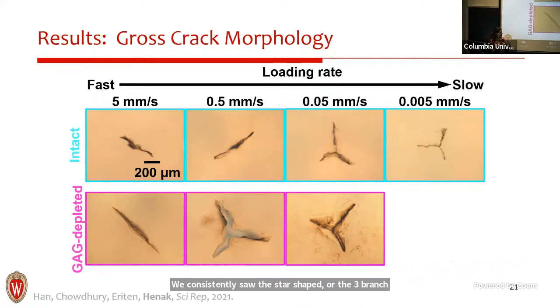The other piece that I think raises some questions, and I'd certainly be willing to have some discussion on this: if you look at the GAG depleted images, this middle one, so the 0.5 millimeters per second for the GAG depleted, you can see that that crack has not fully closed up. We actually saw that in some percentage of our GAG depleted samples, which was kind of interesting. They didn't seem to recover as the other samples did.